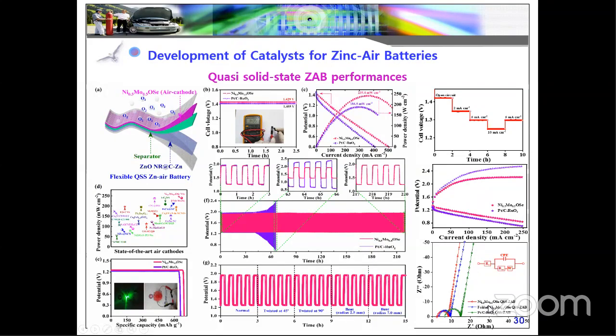So we also tested with the commercial catalyst device. For the electron transport kinetics, indirectly we can say from the electrochemical impedance study, even with the foldable conditions and different foldable conditions, you can see the high frequency semicircle and low frequency semicircle almost retained. From the studies we can say our device has high electron transport kinetics.